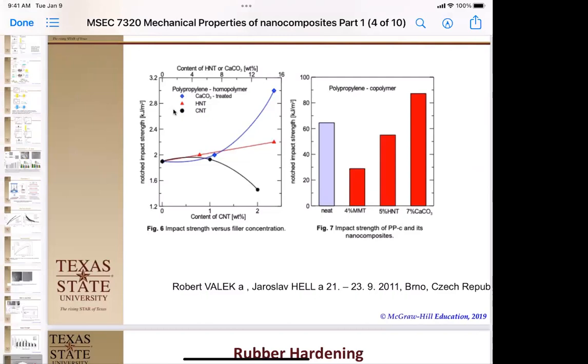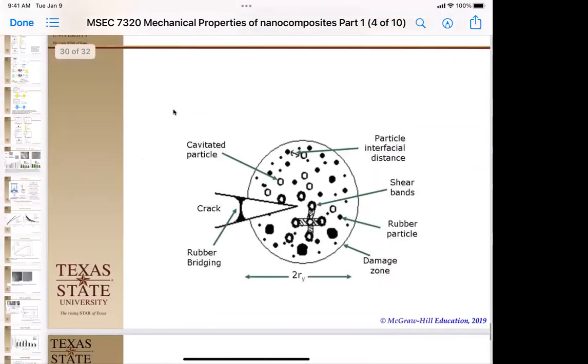Okay, so what happens here? The plates just make it too brittle, and it goes down. The nanotubes make it a little brittle, but it doesn't go down as far. But look what happens with the calcium. The calcium here, it increases, and we can actually even use the CaCO3-treated system, those little soft particles on the outside of the nanotubes help impact strength. Why? Because of the material they produce.